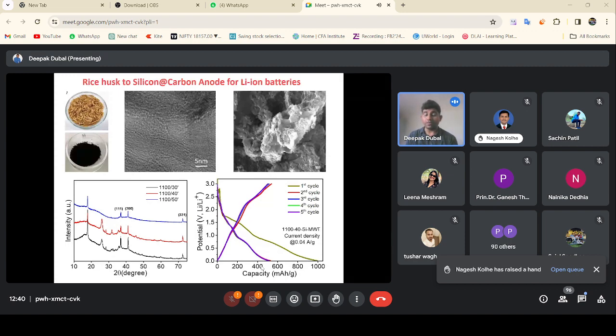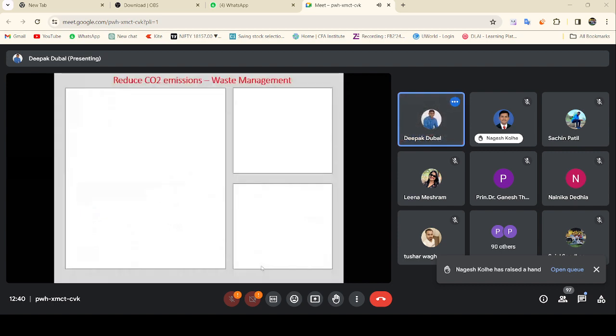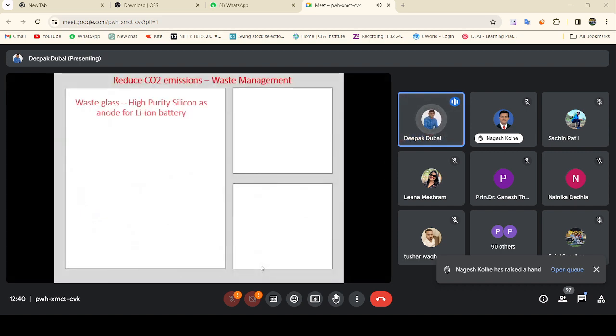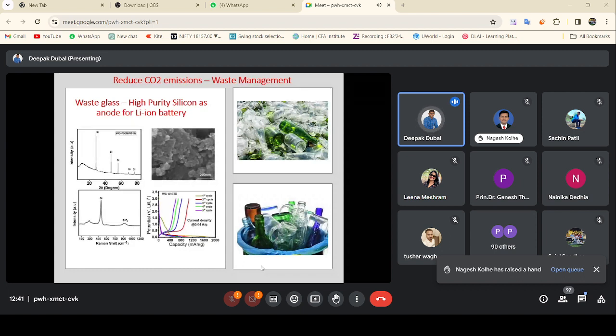And we also got a very interesting capacity. The interesting part of all these investigations is that we did all these processes in 30 or 40 minutes. Most of the time, conventional furnaces take 10 to 15 to 20 hours of reaction time. In a similar way, we also tried to convert simple glass waste.